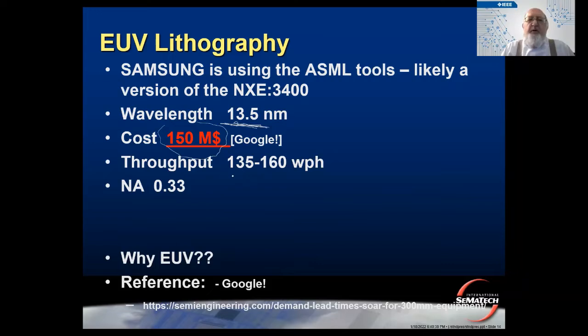Throughput, pretty good, actually, depending on the specific exposure, 135 to 160 wafers per hour, which is quite good. And a numerical aperture that we could hope for a little better, but 0.33 is what that is.